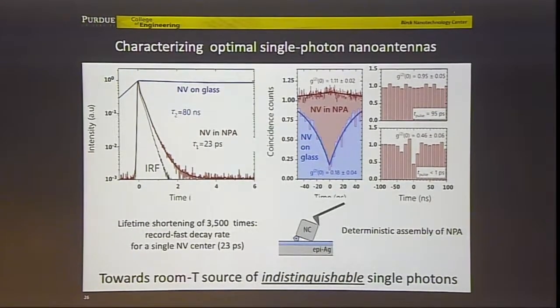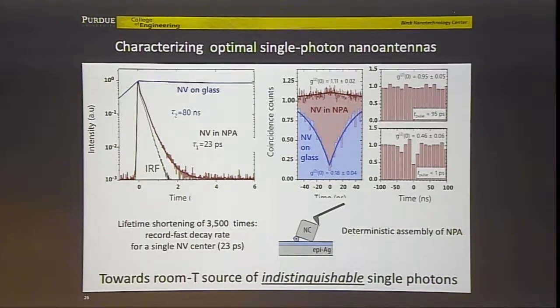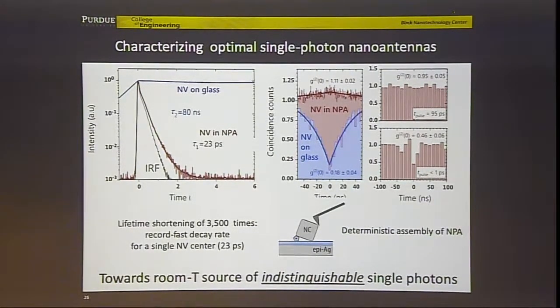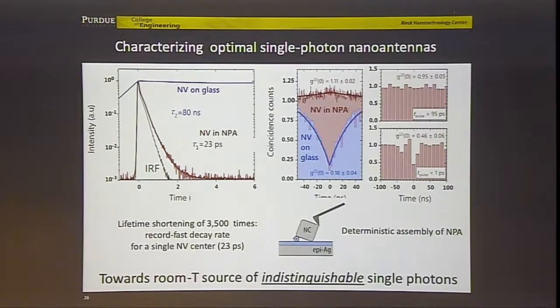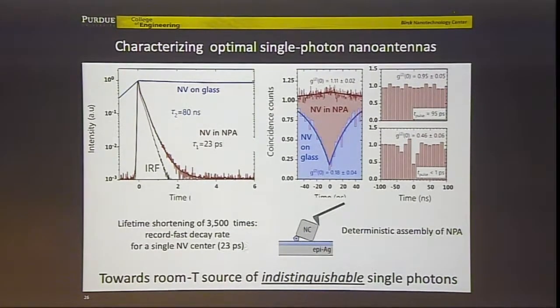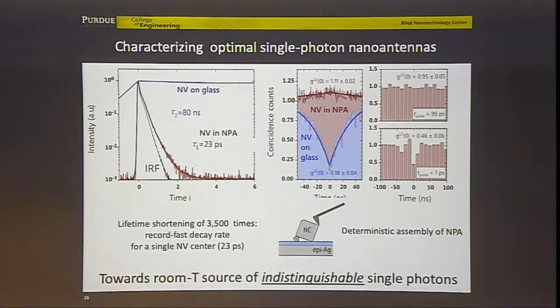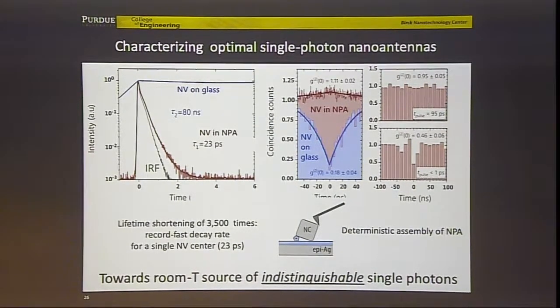So anyway, in this case, this is work in progress. We already see a 3,500 times decrease in the time of spontaneous emission. It means that the rate of spontaneous emission increased by 3,500. We obtained a lifetime as short as 23 picoseconds, which is the shortest ever lifetime seen for nitrogen vacancy. And we proved that this is indeed a single photon source by doing these G2 function measurements.